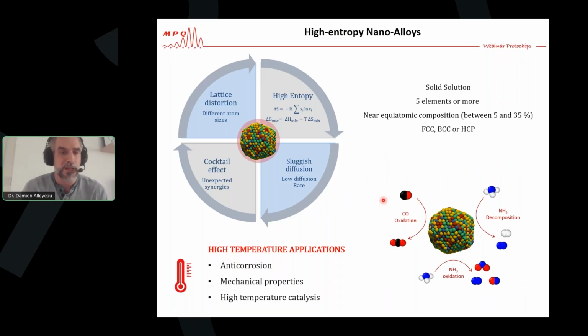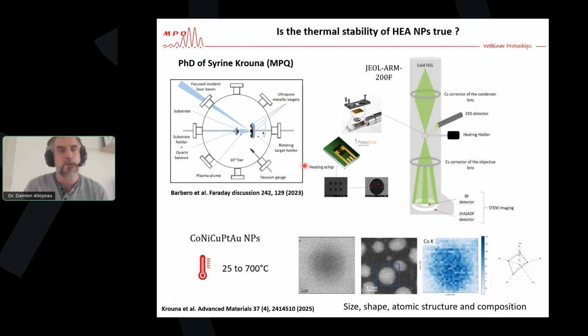The reason for that, there is a lot of speculation about the properties of those particles. They are expected to be stabilized by the entropy, and by the fact that, because of the lot of lattice distortion and the different size of atoms that you have in this nanostructure, they are expected to have a lot of sluggish diffusion. So the first question we ask working on those systems: are they really stable? Is the stability of high entropy nanoparticles true? So we designed an experiment using the very highly stable gas cell system from Protochips, an in-situ TEM experiment, to verify these hypotheses. Are they really thermally stable?